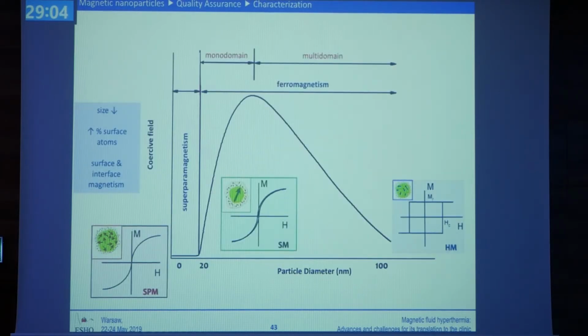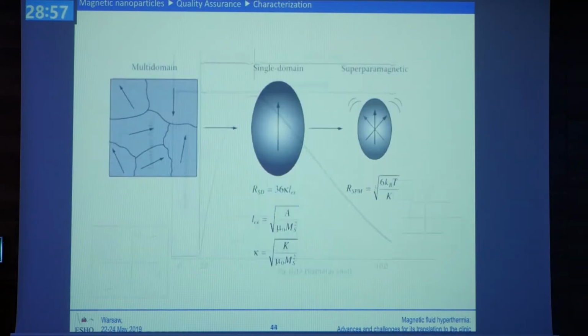Okay? So, do we know the radii at which the magnetic behavior of the nanoparticle changes? Yes, we know. There are some radii where you have superparamagnetic behavior. In this behavior, every dipole, every compass behaves on its own in the atom. Then if you go from right to left, you have single domain, you don't have any magnetic walls. If the nanoparticle becomes larger, all the dipoles, all the small compasses, behave as one. And then when you have a larger nanoparticle, you can have different single domains inside it and also some magnetic walls forming inside your nanoparticle.